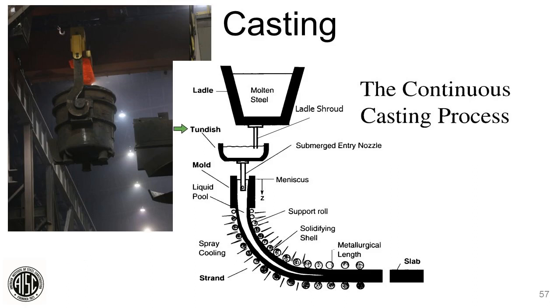And what that does, it distributes the liquid steel over however many molds we're running. Sometimes we're running 4 molds, 1 mold, 2 molds, depends on how many we got. So when it pours out, some shops will go through some sort of submerged entry nozzle. It can be open stream. Depends on what grade of steel you're making there. It'll go into the mold, which is a copper-cooled mold. It oscillates up and down as it holds a certain level.